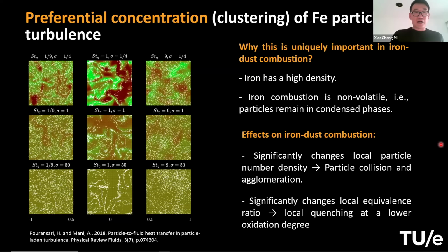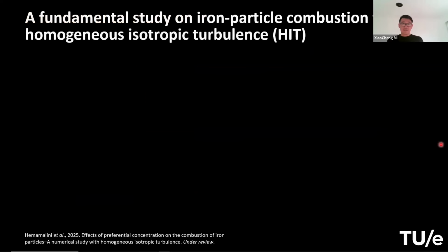One thing is that locally the particles can be highly concentrated so that they can collide and form agglomeration, right? This is one. And the second one is also because of this localized concentration, locally you can have a very fuel-rich region, and the iron particles may locally deplete the available oxygen. This can lead to quenching or just a lower oxidation degree. Whether this may happen in reality or not, we don't have any in situ or very direct measurement yet, but we did some fundamental study based on CFD, right?